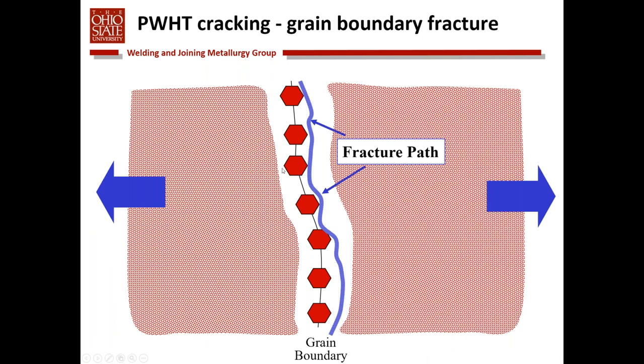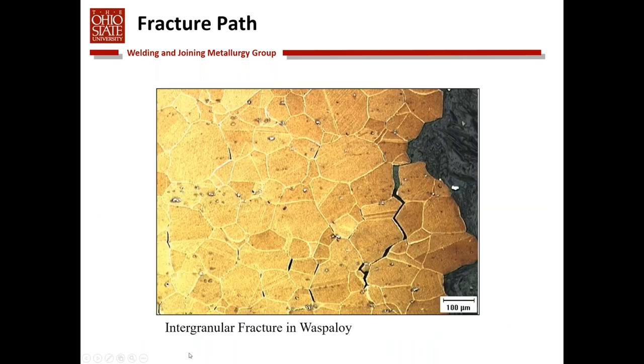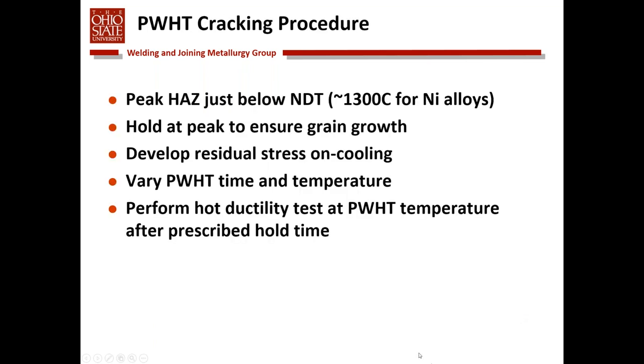So the cracking occurs along grain boundaries. The exact fracture mechanism is still subject to some debate, but the cracking does occur along grain boundaries. Here's an intergranular fracture in a nickel-based alloy, Waspaloy. This is a Gleeble test sample, and you can see the cracks that have formed along grain boundaries during the test.